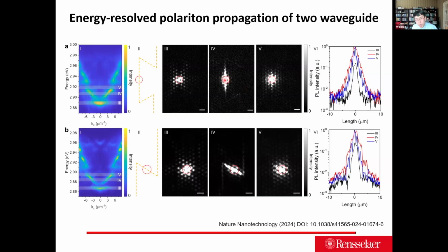So with the polariton, we only pump in the right circle region, and then they start to propagate out. They roughly propagate out a few microns, if you consider the natural e, like 30% or 20% of the original intensity. So a couple of microns. But if the camera can see it on a logarithmic scale, you can observe a propagation of about 10 microns, or even longer, barely by eye. But if you pump the whole channel area or the whole bulk area to make it condense, because everywhere becomes gain, they essentially propagate forever without damping.